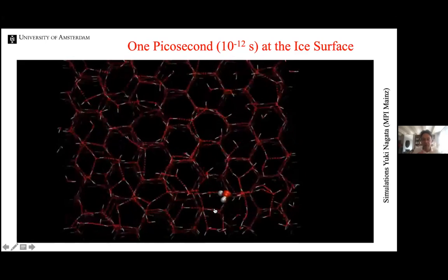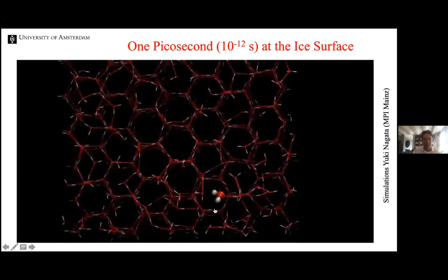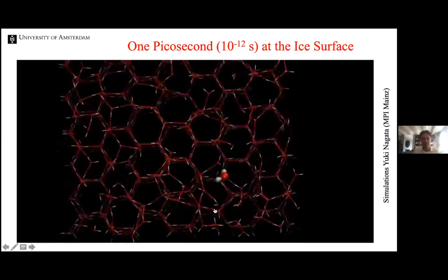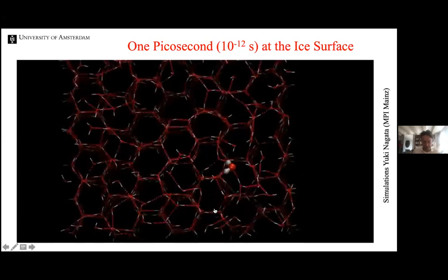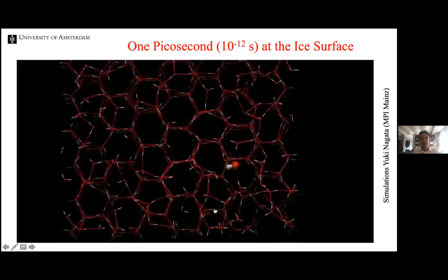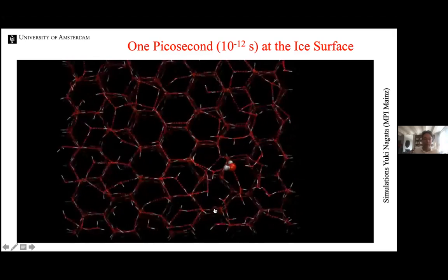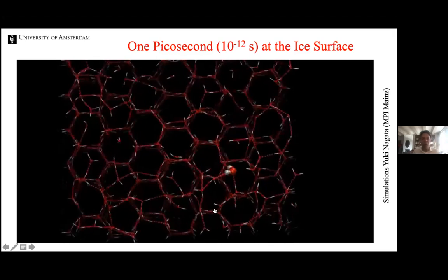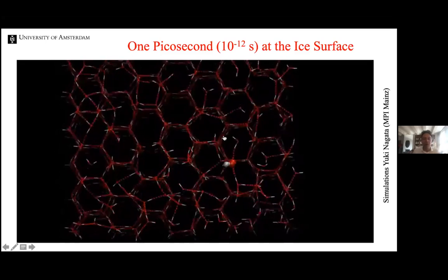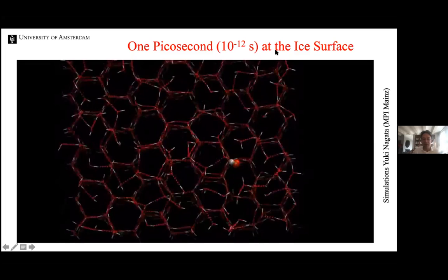And so it turns out that there's different types of water molecules at the ice surface. There's water molecules that have 2, and there's water molecules that have 3 hydrogen bonds. And these molecules that have 2 hydrogen bonds are so mobile that you can see them moving over the surface in even less than a picosecond. And so that means that it's sort of a 2D gas, if you like, of molecules that are still within the crystalline lattice, but that are so mobile that they can change places very easily.